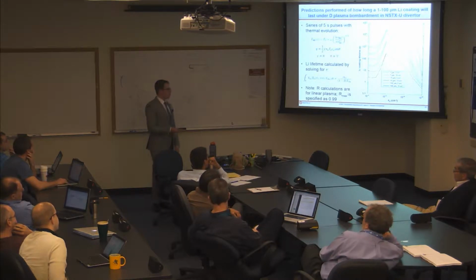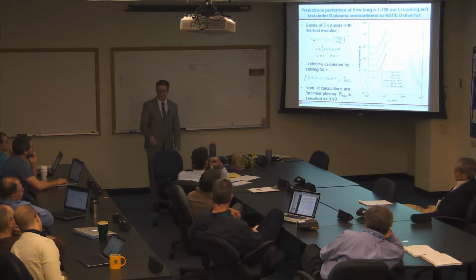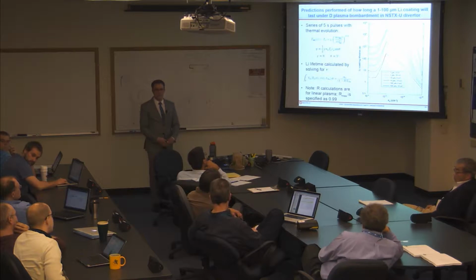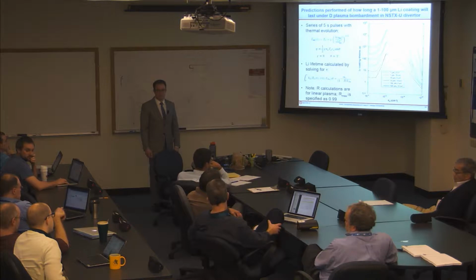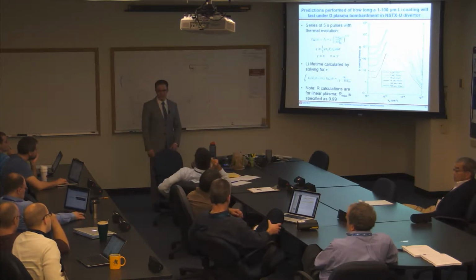These are assumed to be clean, or no impurities at all mixed in with the lithium? It's just pure lithium? It starts out as pure lithium, but it incorporates the deuterium implantation, of course. It doesn't incorporate oxidation. Or carbon, for example. And so actually the experience of the old NSTX experience of lithium on graphite is different, right? This is assuming lithium on TZM. So actually, we should be forbidden to even dream of comparing this to the NSTX experience.